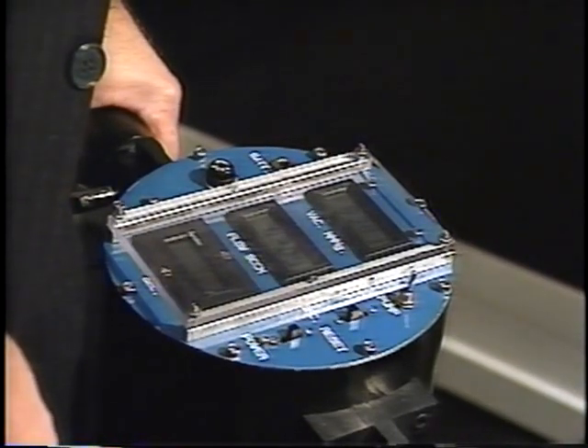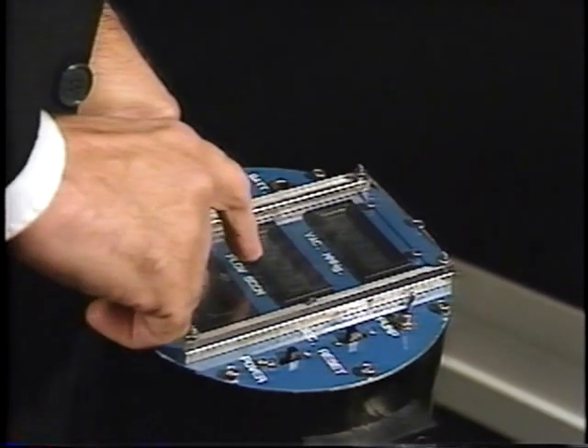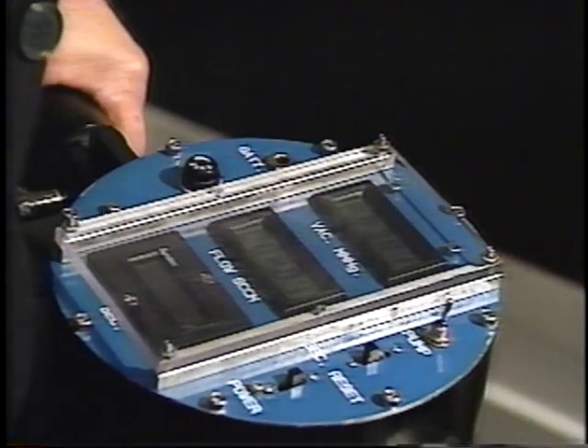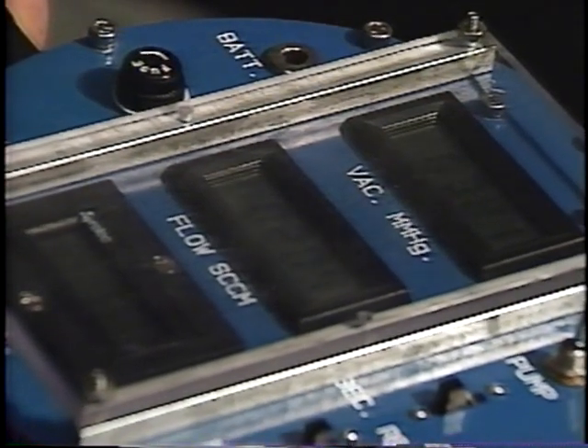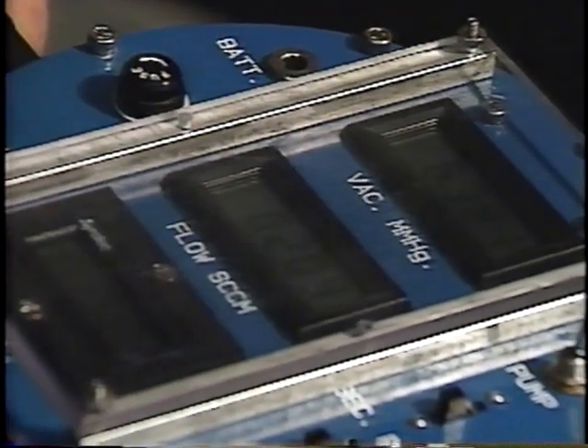This is the elapsed time of test. We're now testing the silica fume concrete. As you see, the flow level is down to 2 cubic centimeters per minute. This is a very low level. Anything below 5 is indicative of very dense, impermeable concrete, and this is fairly close to 0, indicating a very dense and impermeable surface.